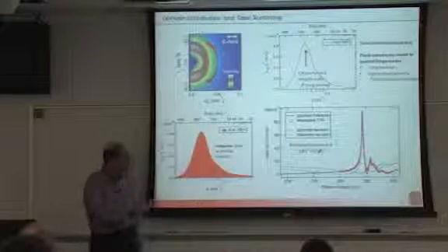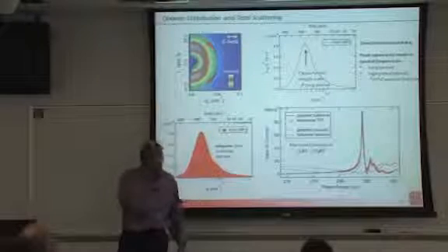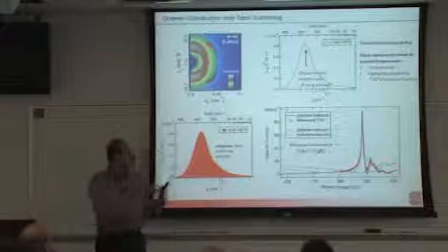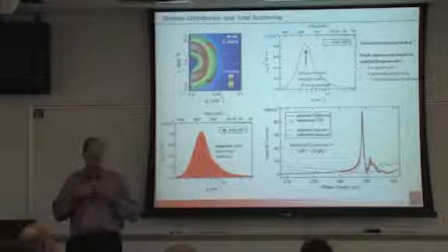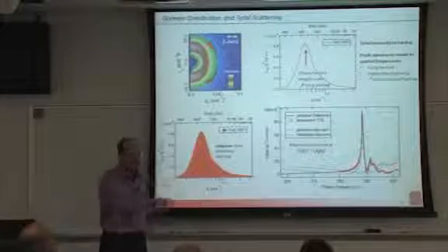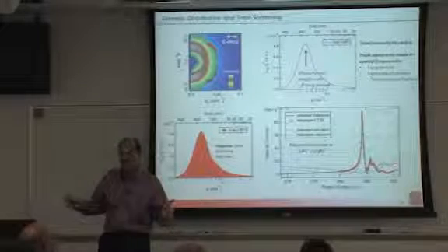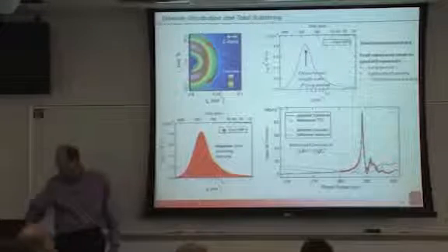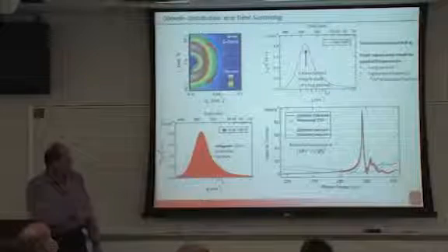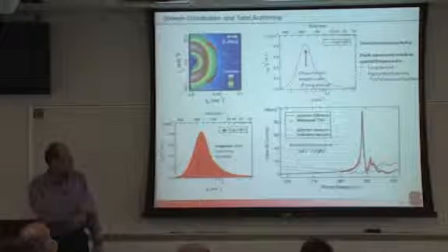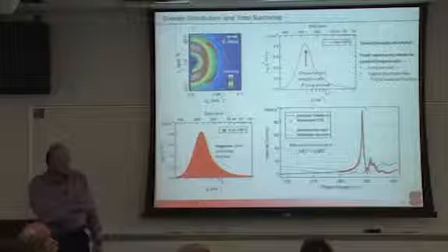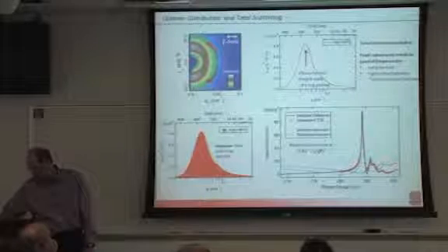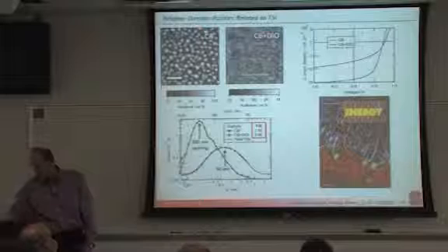So in this case, we have excellent correspondence to the materials contrast, and that means I know that whatever scattering distribution I get here is actually from the compositional fluctuations in the sample. So this is a nice thing that you don't have with hard X-rays, and it's hard to do with neutrons as well. And it's particularly important later on when you have additional scattering from orientational correlations.